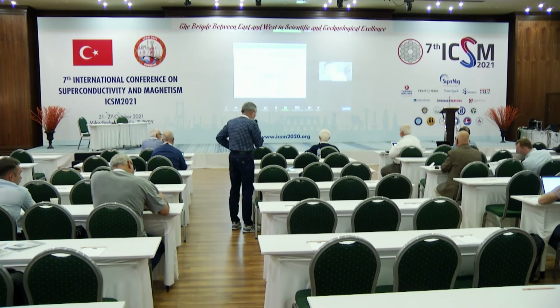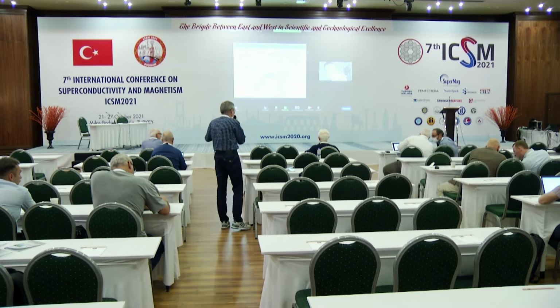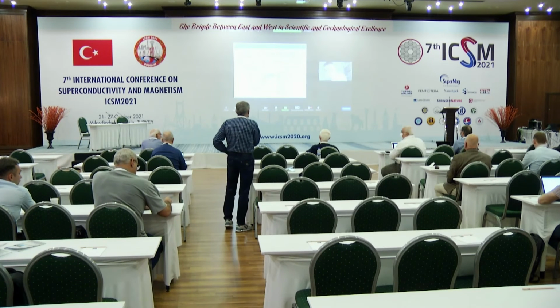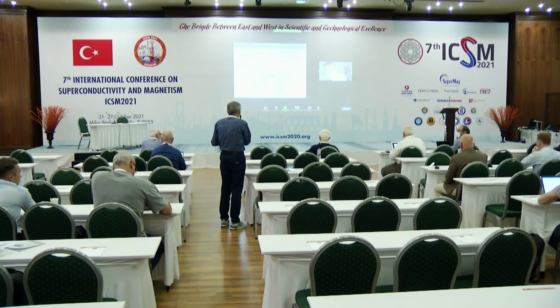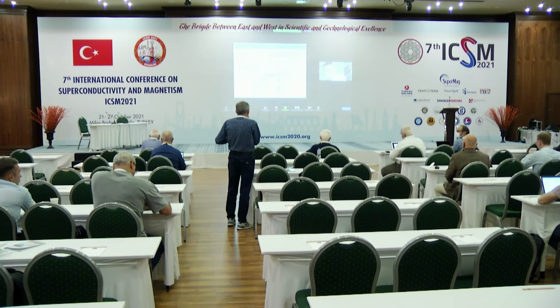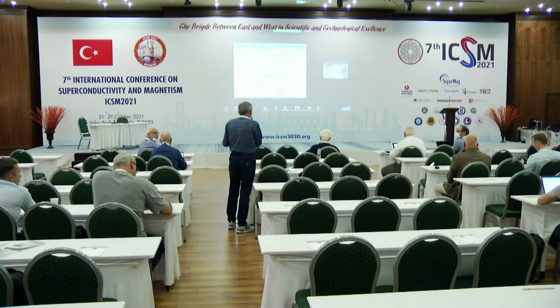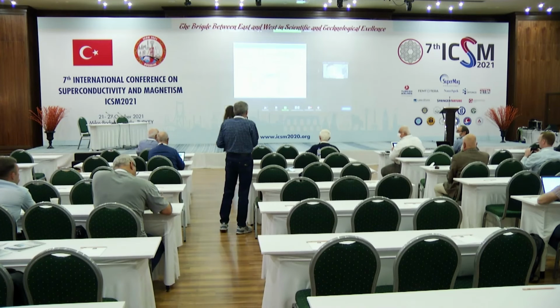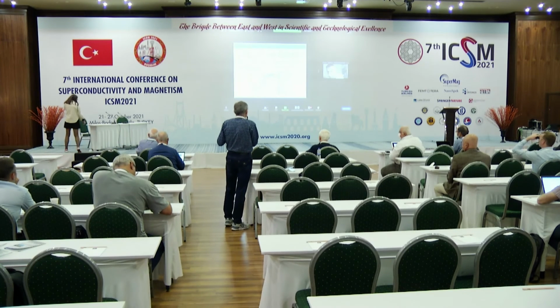May I have a comment, Evgeny? I'm sorry, but you have estimates for metallic hydrogen that the BCS formula may give a Tc of 15.5 Kelvin, but you have nothing to do with the BCS formula. If it is realized, it should be a very strongly coupled superconductor, and you must deal with the Eliashberg equation. Ashcroft's estimates are for room temperature superconductivity because it's a very strongly coupled superconductor, and superhydrides are also very strongly coupled superconductors.